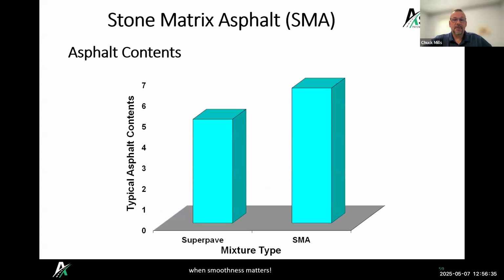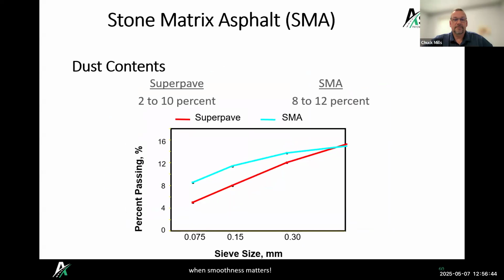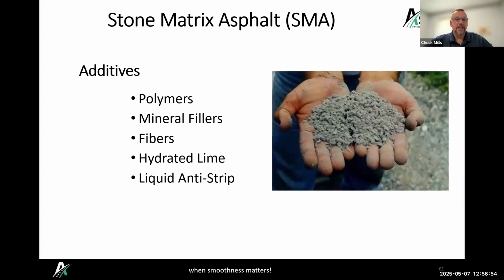Asphalt contents are typically higher than the regular Superpave mixes. Again, it's to get that rich mastic in between the stone on stone contact. You also have a higher dust content to soak up more of that liquid asphalt for the mastic in between. And then we're typically adding polymers, mineral fillers, and fibers, hydrated lime, liquid antistrip. That's all part of that mastic that really makes this a tough mix.